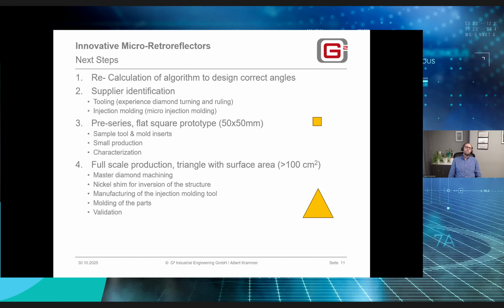The next planned step is a kind of a prototyping tool with a small surface of about 50 by 50 millimeters. And the target is here to really go on the injection molding machine to try out if the optics are coming out, if the quality of the tool inserts is good, if all the coatings are good, how many pieces we can produce without quality loss, and of course one loop in the light lab to characterize the lighting behavior.